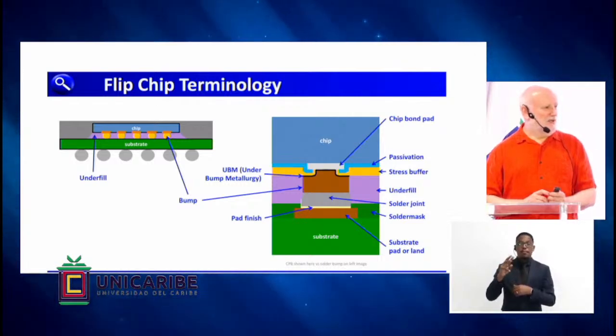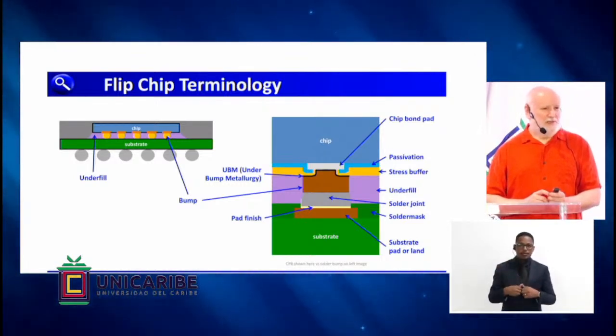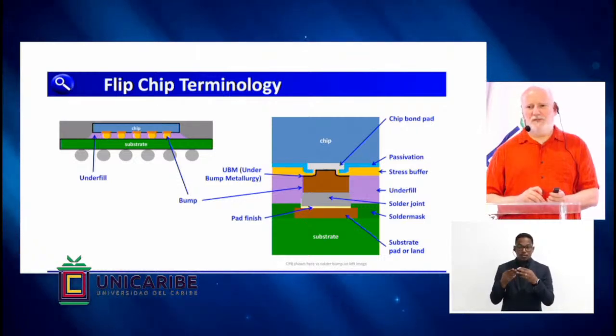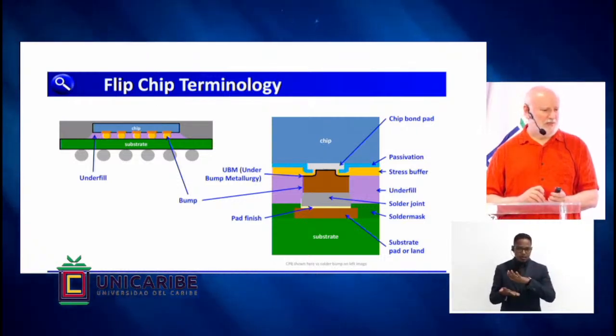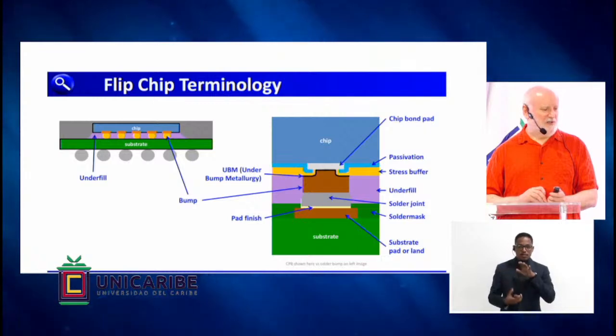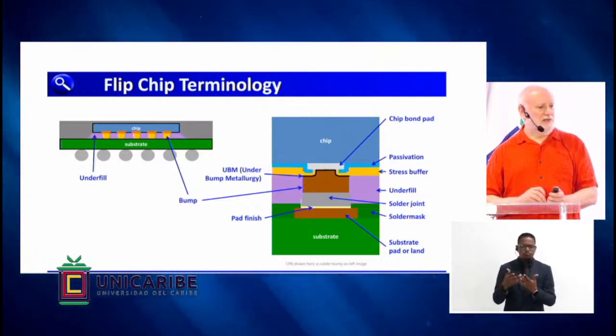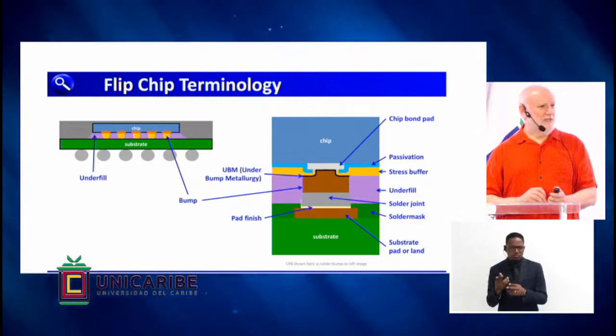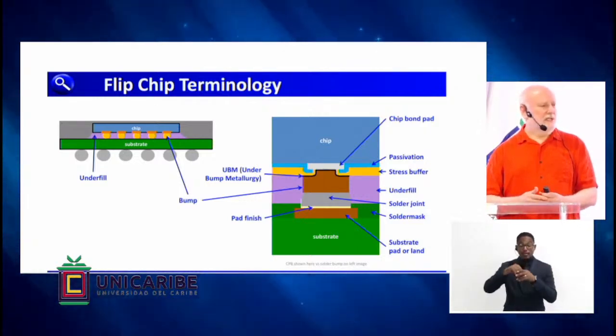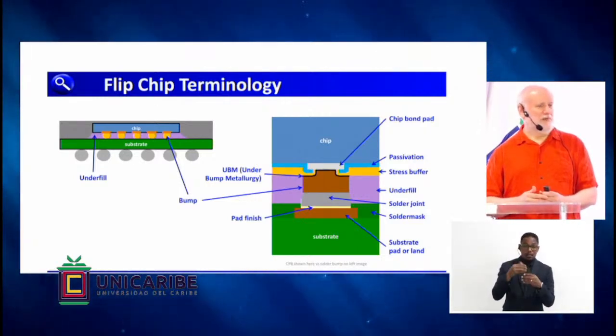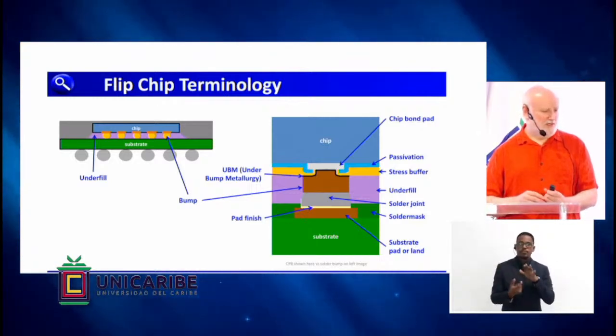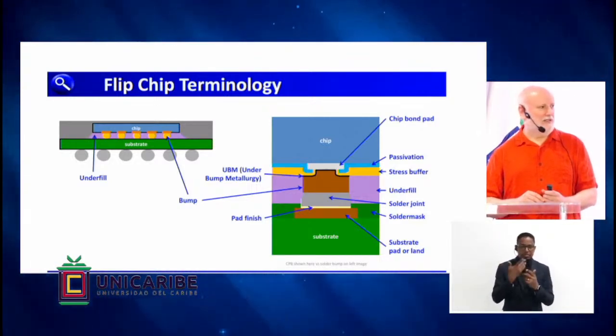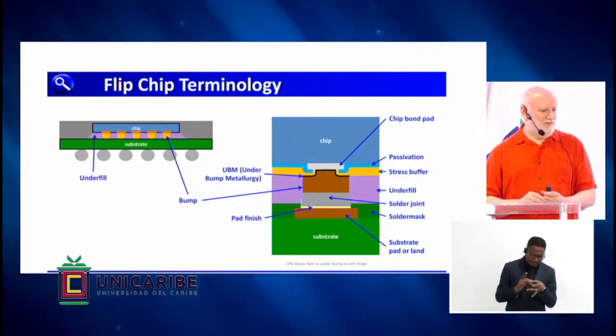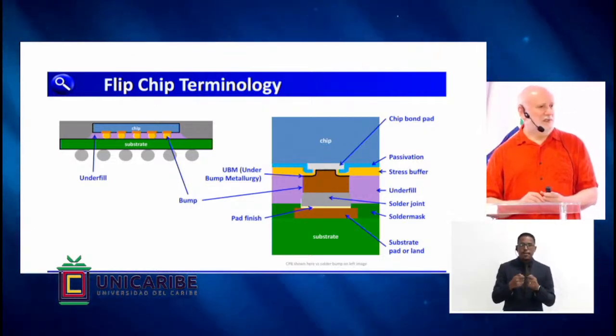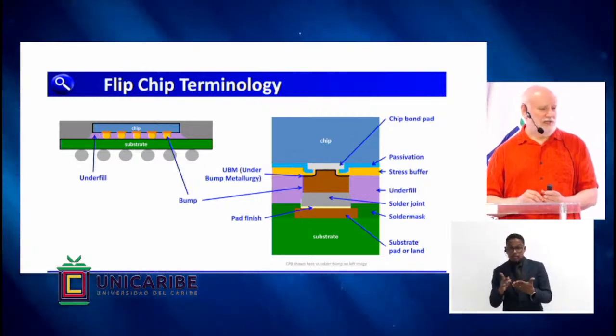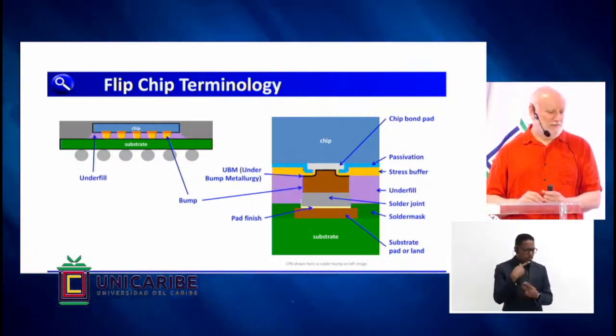There's often what we call an underfill material, and that material actually was one of the things that allowed flip chips to come into widespread use. So prior to the use of underfill, if the chips got too large, if the chip was on a laminate substrate, the differential expansion when temperature changes between the chip and the substrate would put a lot of stress on the bumps and cause bump failures. They would crack. And somebody tried and found out that underfill would reduce this cracking significantly. And so that allowed the widespread use of flip chip.